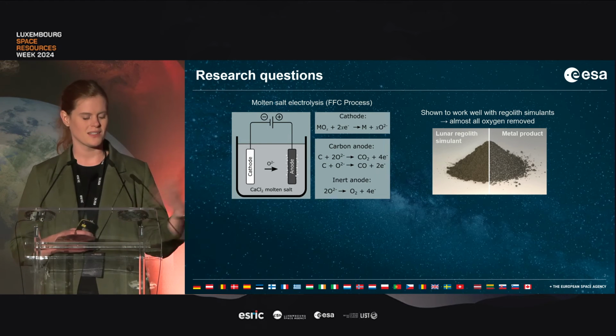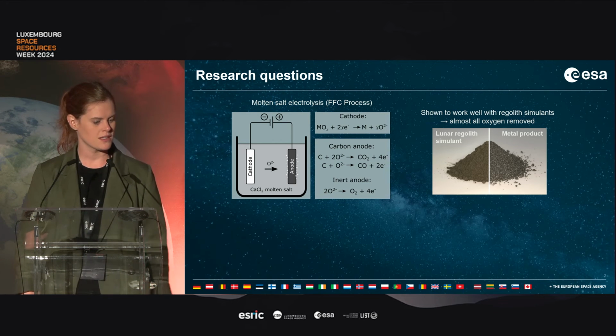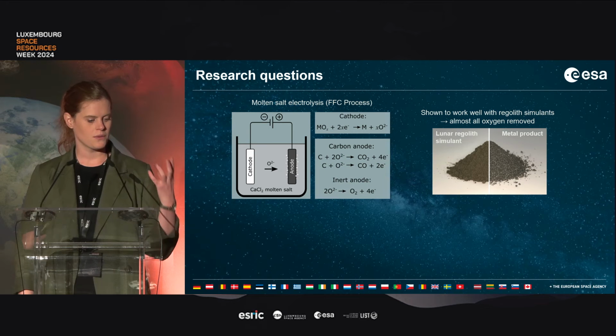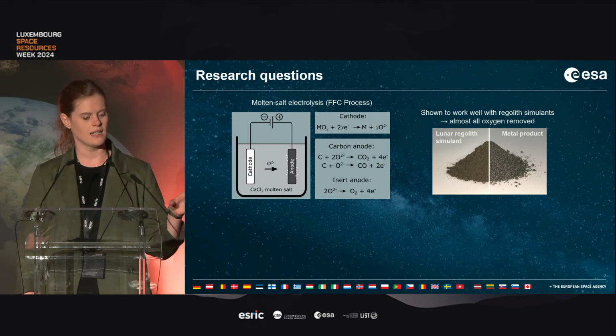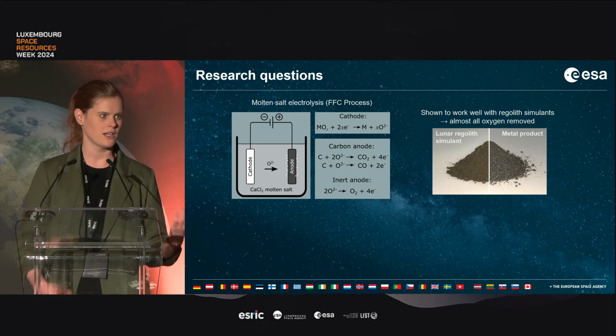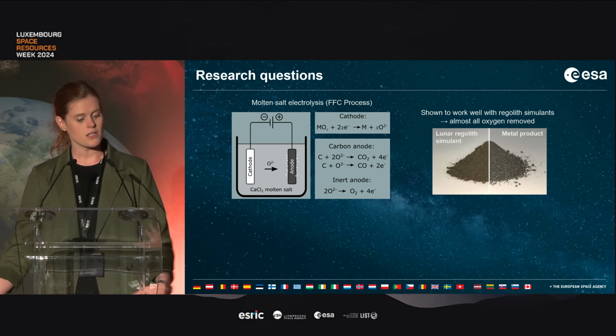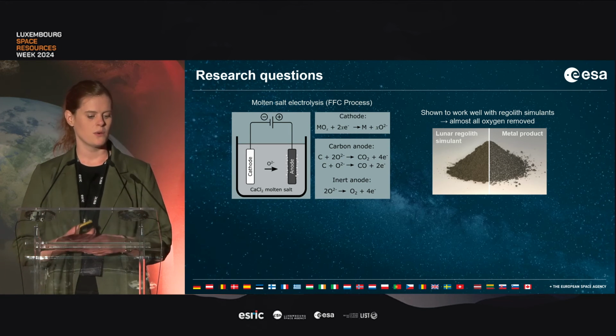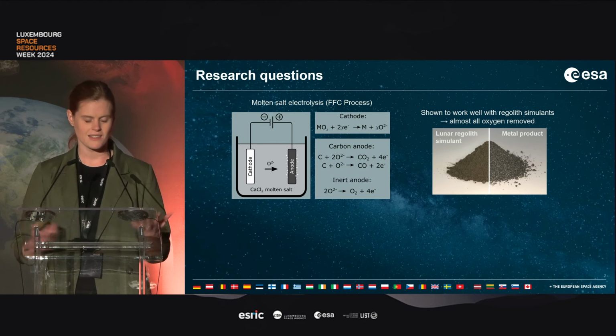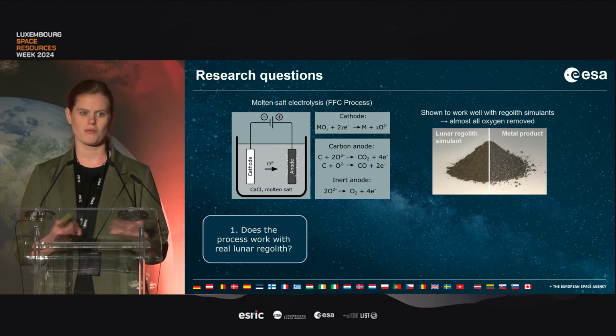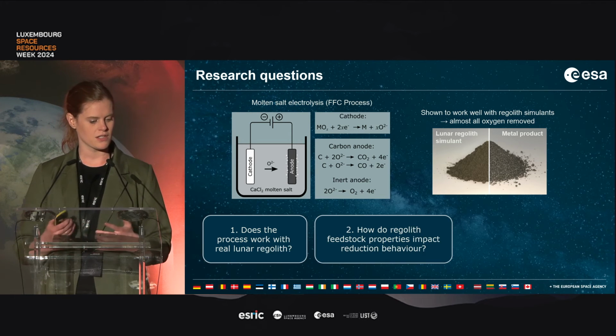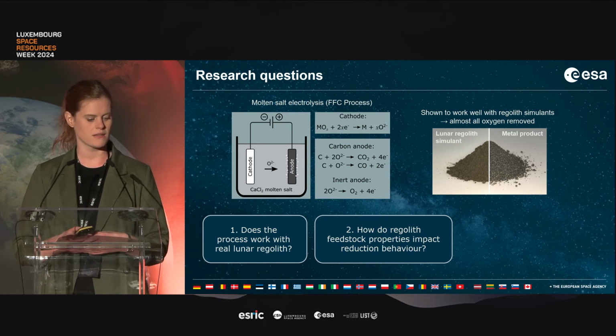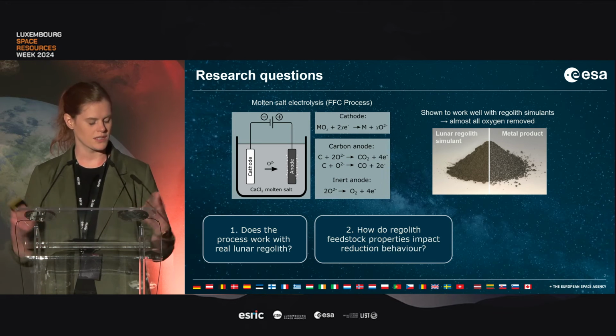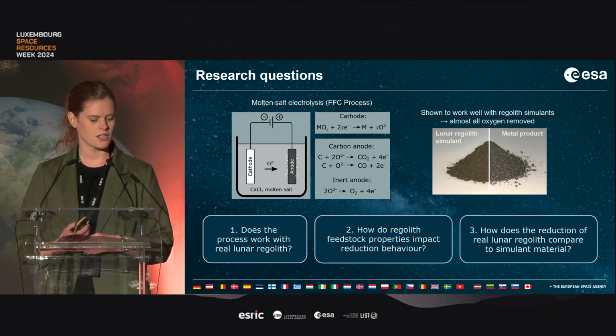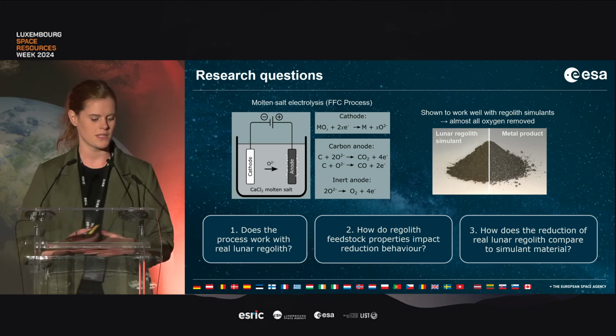I probably don't need to go into this given the previous talks in the session, but just very briefly, molten salt electrolysis, also known as the FFC process, is in a bath of calcium chloride salt. The regolith is going in at the cathode in the solid state, and in this process we can use a carbon anode or an inert anode if we're looking to target oxygen directly. It's been shown to work reasonably well with a simulant material where we can remove almost all of the oxygen, but of course that leads to the key question: does the process work with real lunar regolith? We also wanted to address the question of how the regolith feedstock properties impact the reduction behaviour, because obviously the moon is not a homogeneous body, and also how the reduction of real material compares to the simulant material behaviour.